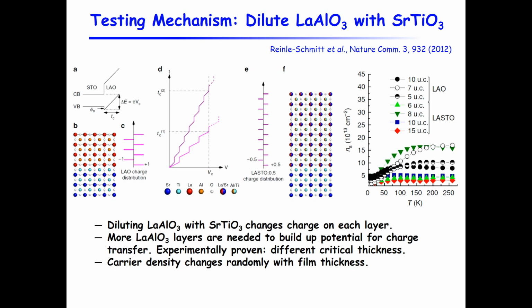This is an example that I want to show from the Geneva group, who dilute lanthanum aluminate with strontium titanate. And so when you dilute, you grow the mixture of lanthanum aluminate and strontium titanate, what you do is change how much charge is in each of the layers. And if you just grow lanthanum aluminate, you would have each layer carry either +1 or -1 charge, and then the field diverges when the thickness increases.